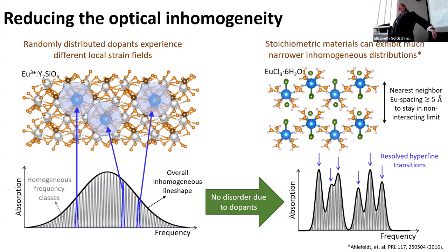It's a really good question. In fact, there's a series of papers from this group on these kinds of materials, where for making the individual atom line widths narrower, they deuterate the water, for instance, because that changes the phonon spectrum. So yes, but unless you're really floppy, just cooling is fine.